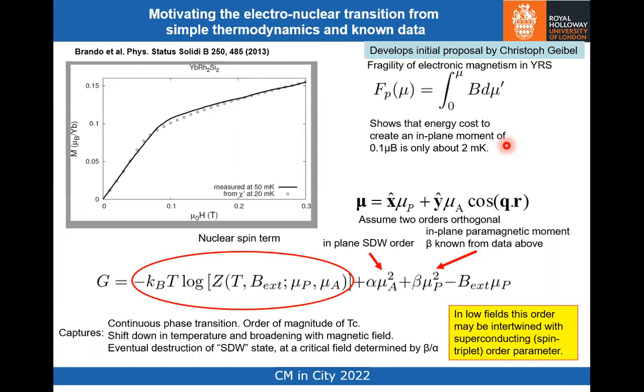That's a much smaller energy scale than the Néel temperature energy scale. So this is very unlikely to be anything to do with canting of the pre-existing electronic order at the Néel point. There's some other fragility of the electronic magnetism in YbRh2Si2, I like that word, fragility, such that these tiny in-plane fields with energy scales of only 2 millikelvin can do something. So if such small magnetic fields can do something, then maybe the nuclear spins can also do something. And so what we did then is to write down a free energy of the following form.